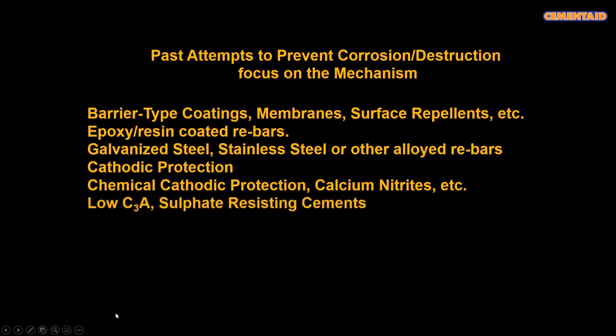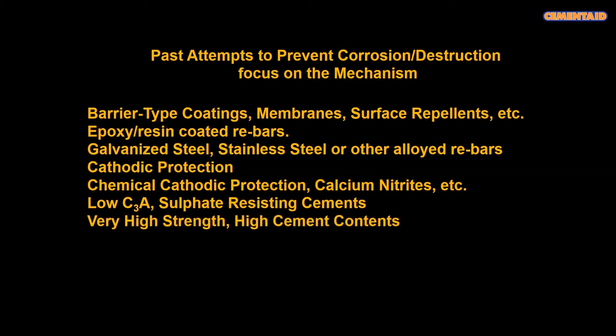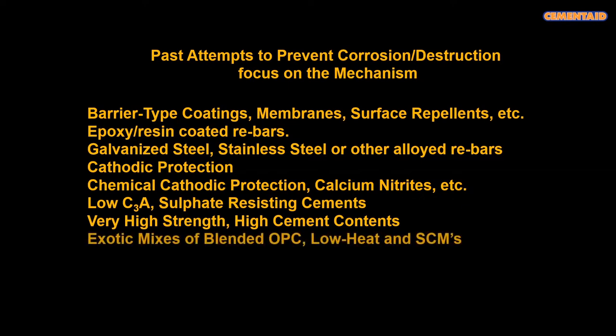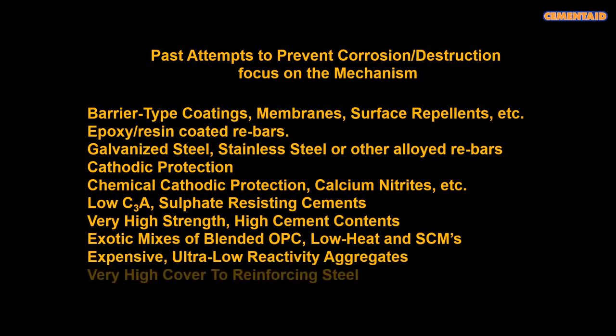If you're worried about sulfate attack, of course, low C3A or sulfate resistant cements or blast furnace slag or other means of reducing the C3A. Very high strength concrete, high cement contents, will densify concrete obviously, but they will do very little to actually prevent water absorption. Exotic mixes with blended cements, low heat cements, special secondary cementitious materials. Again, all very helpful, but they don't completely solve the problem.